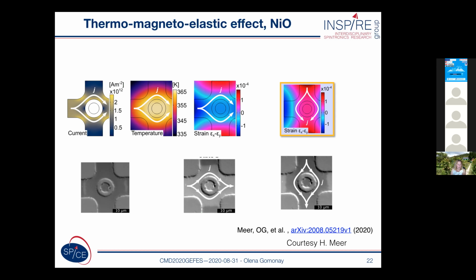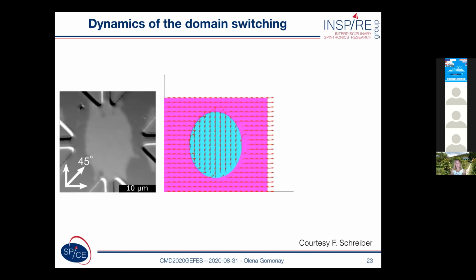And for this, we also tried to simulate the dynamics of switching using the equation of motion for the antiferromagnetic vector in presence of magnetoelastic interactions induced by the current. So we started from the 90 degree domain shown with the blue ellipse in the central figure, which simulates the experimental situation, and arrows here show the direction of the Néel vector.